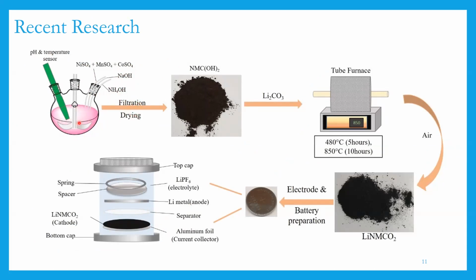Normally during synthesis, you start with a pink precipitate. But when you dry it in air, this metal hydroxide easily oxidizes, and so you get a brown precipitate. This impurity is removed when you treat it with lithium and do high temperature calcination. And then finally, you get this black powder, which is the lithium nickel manganese cobalt oxide, which you can then use to perform your electrochemical analysis.